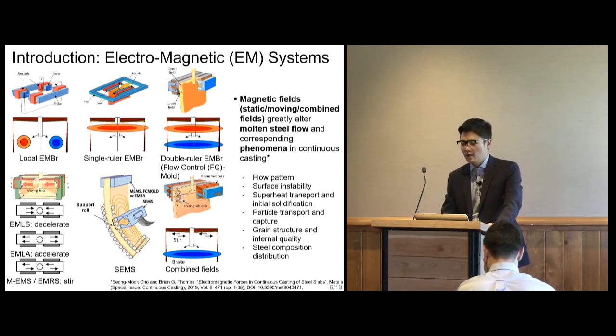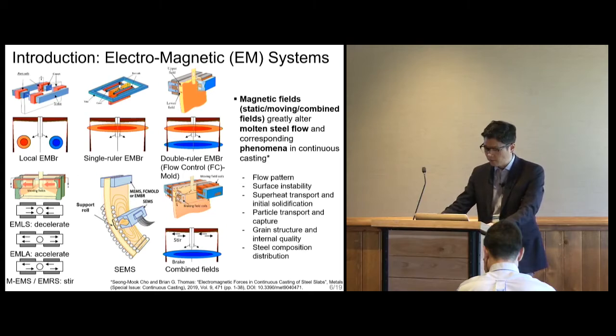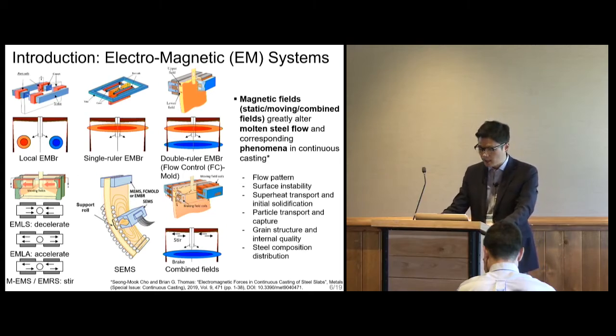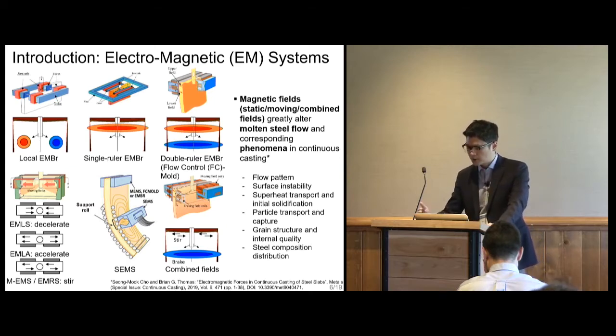So to reduce the defects explained in the previous slide, several electromagnetic systems have been used. They control the flow pattern, surface instability, superheat transport, initial solidification, particle transport and capture, grain structure, internal quality, and steel composition and distributions. So we will show some of our results here for double-ruler EMBr static magnetic field and the mold electromagnetic stirring moving field effect on the multiphysics phenomena.